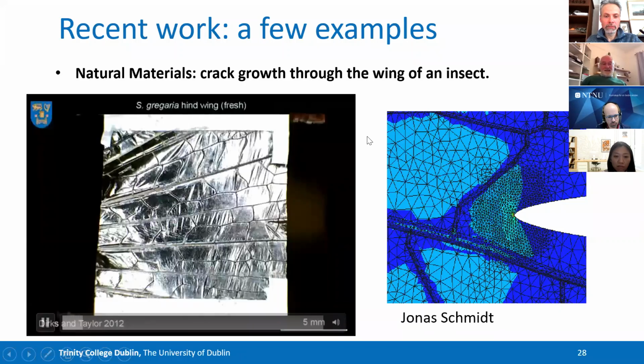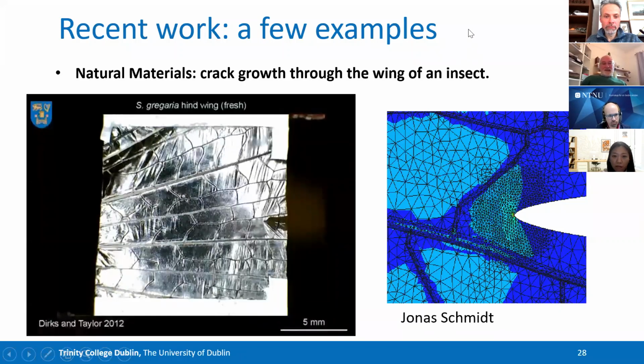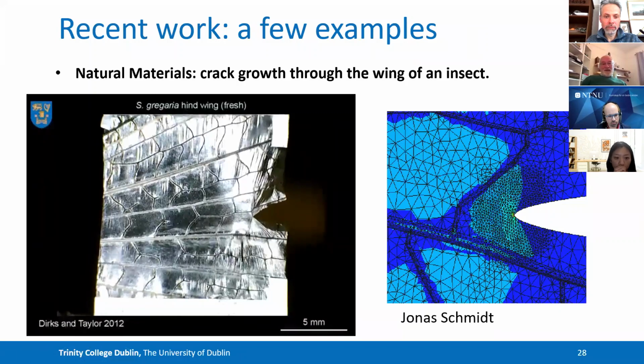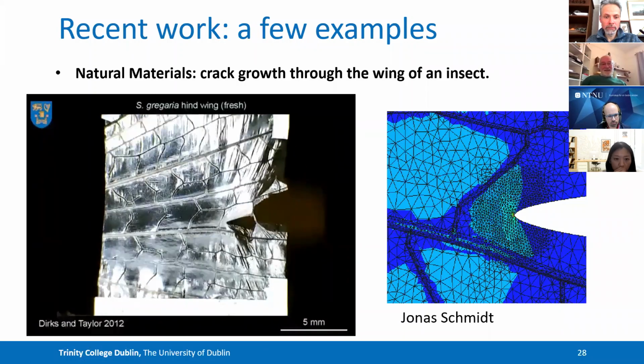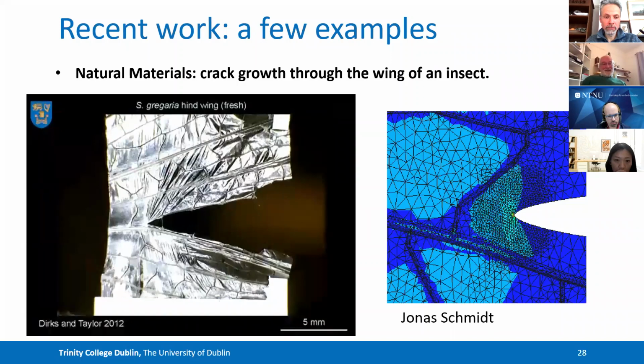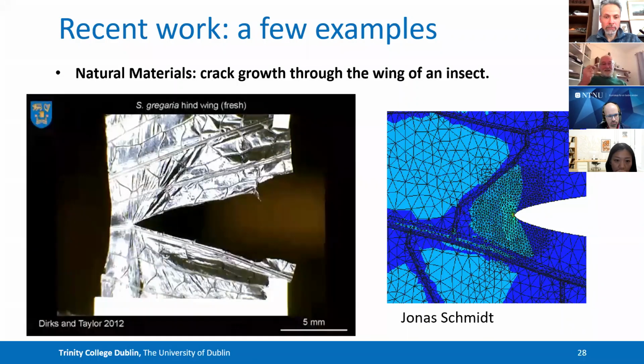This is a test where we are passing a crack through the wing of an insect, and you can see the crack hitting the veins of the wing there and passing through it and being interrupted. And that's a classic example of that finite crack extension that I was talking about. We made a finite element model of that. My researcher, Jonas Schmidt, showed that the TCD could be used very nicely to predict the experimental results in that rather weird example, and we've used it for quite a lot of different natural biological materials.